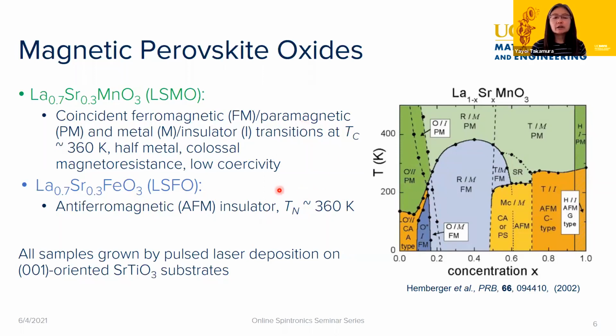And so that was one of the motivations we had for looking at these multi-layer structures. In some of the work later, I'll also show lanthanum iron oxide, which, without the strontium doping, the only difference is that it has a much higher Néel temperature. And for everything that I show, all these samples will be grown by pulsed laser deposition on 001 oriented strontium titanate substrates.